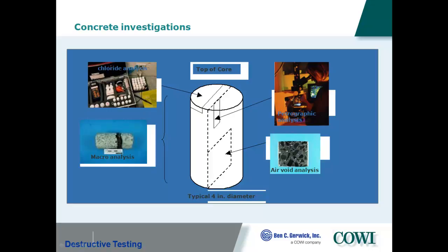You can use some of it for chloride analysis. This is an equipment, rapid chloride analysis. You can also have titration methods in lab. We can look at the core itself and describe the components and what it consists of, visible signs of deterioration. We can do air void analysis by point counting methods. So you get the air content and the air void distribution. And we can also have thin sections prepared, which are only 20 microns in thickness, so that in a microscope, we can look through these.